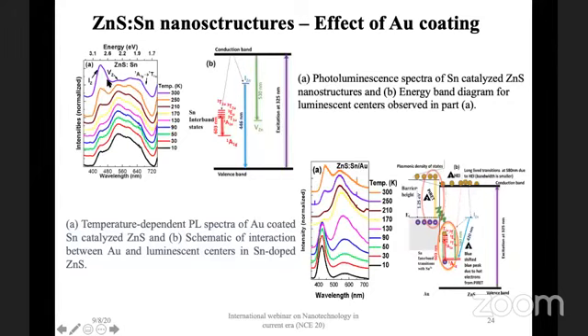Now what happened when we coated with the gold, we see that at low temperature all the bands which were very strong in pure zinc sulfide nanostructures doped with tin are suppressed, and the blue became very strong, and then the green and the red emerged as the temperature rose. So this is again explained in terms of this plasmon induced resonant energy transfer mechanism, which is given on the right side. How it plays its role is quite complex.